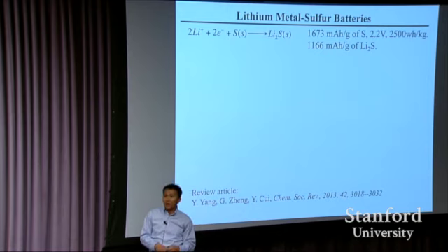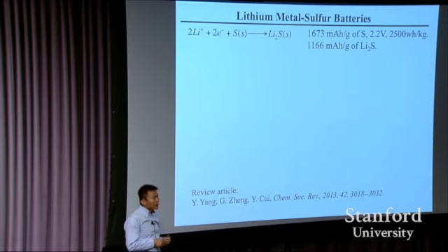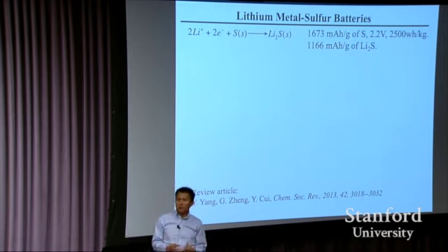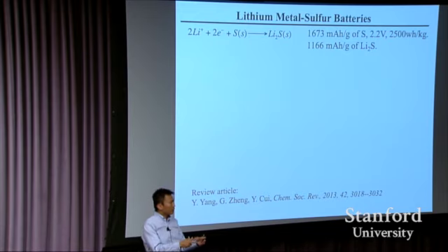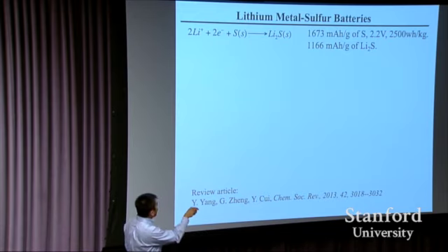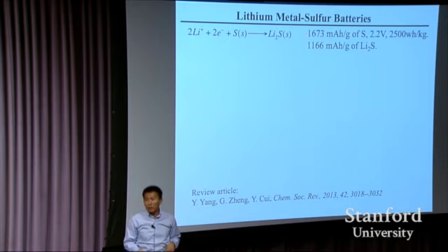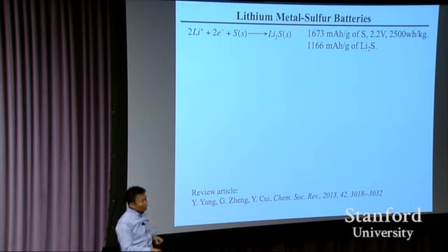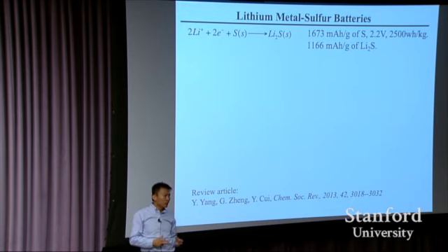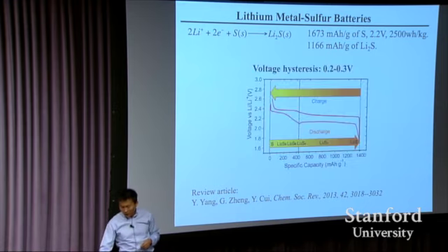Now let me move on to the cathode. So silicon is an anode. For the cathode, I'm going to move quickly to really show you that it's possible to have the next generation of high energy batteries. In order to have the full battery's energy density go very high, sulfur is very attractive. Sulfur has this 1700 milliamp per gram capacity, 10 times that of lithium cobalt oxide. The voltage is half. So you are talking about energy that can get to 4 to 6 times the existing battery technology, very attractive.